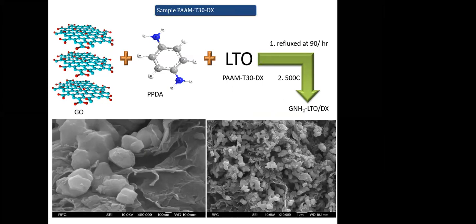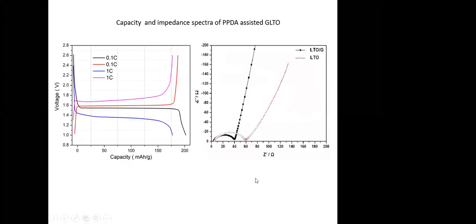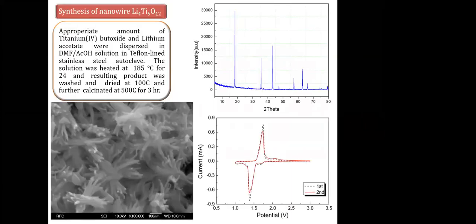composite material with LTO. And generally LTO has 175. So once you are adding graphene up to 4%, we are going to get nearly 180 mAh per gram capacity. And you can see from the impedance, because graphene being conducting in nature, it has reduced the impedance of the cell.